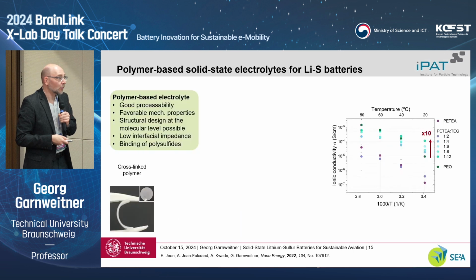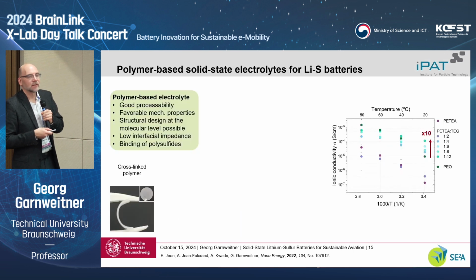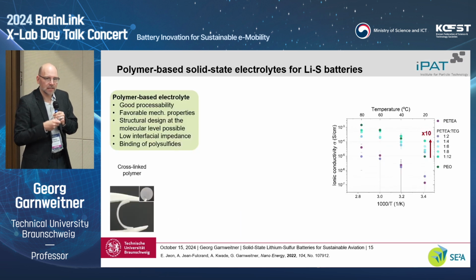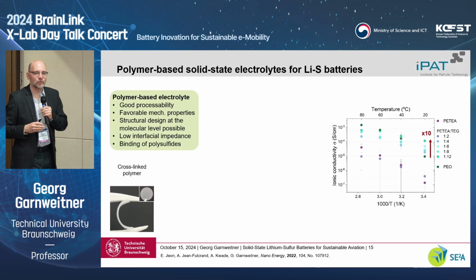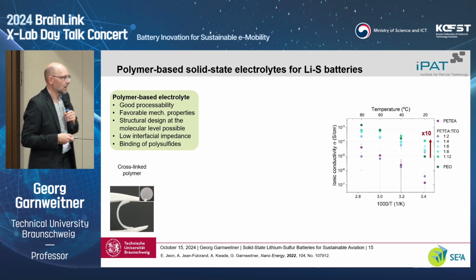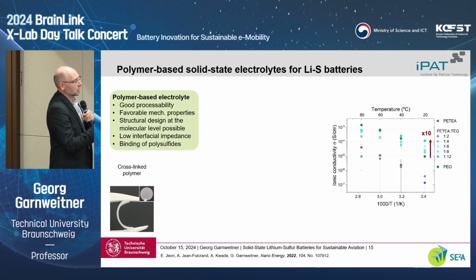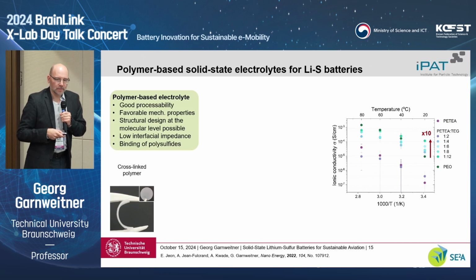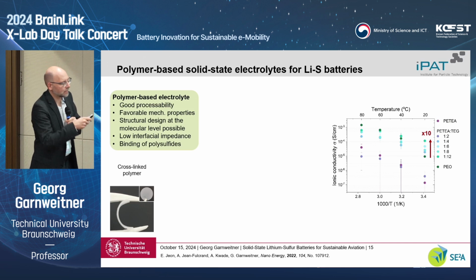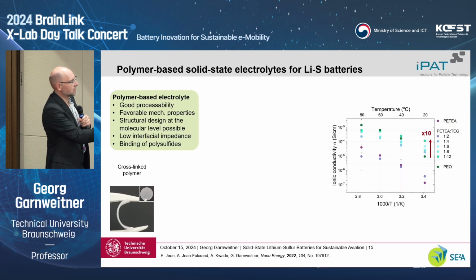But the big problem with the polymer is that it has a low ionic conductivity at room temperature. So there is a strong dependence on the temperature, and typically such batteries always have to be operated at higher temperatures so that they have a good conductivity and are efficient. Well, we designed a special type of polymer. I won't go into the details for the sake of time today. I will present that in more detail in the next days.